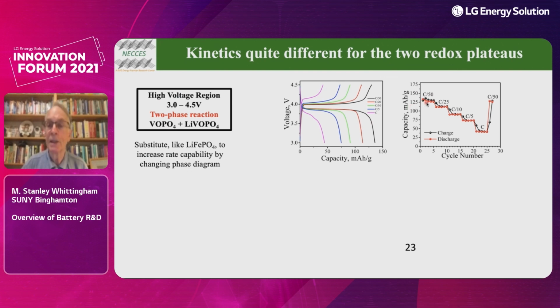And you can see here's a C/50. If we go to C rate, we've lost over 50% of the capacity. So this is not a high rate material. We believe we should be able to substitute this material just like the olivine lithium iron phosphate. Pure lithium iron phosphate is not all that good. A little bit of substitution in there and nanosizing makes it extremely high rate. And when we do that, it basically changes the phase diagram.